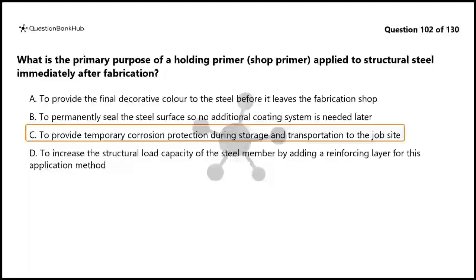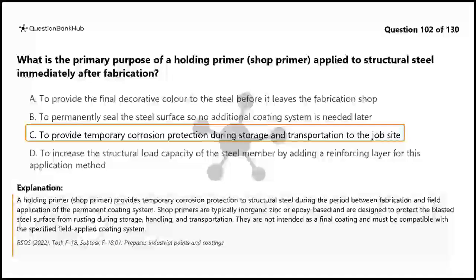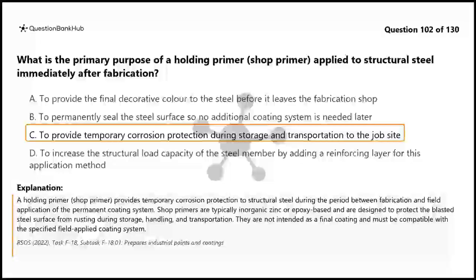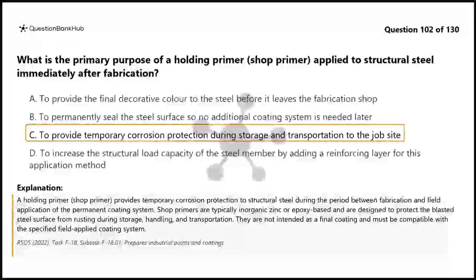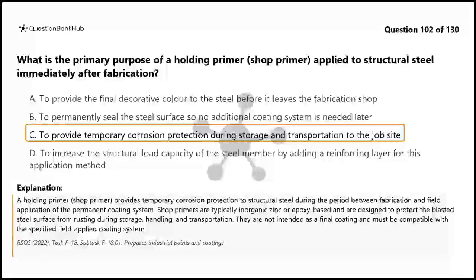The correct answer is C. A holding primer, shop primer, provides temporary corrosion protection to structural steel during the period between fabrication and field application of the permanent coating system. Shop primers are typically inorganic zinc or epoxy-based and are designed to protect the blasted steel surface from rusting during storage, handling, and transportation. They are not intended as a final coating and must be compatible with the specified field-applied coating system.